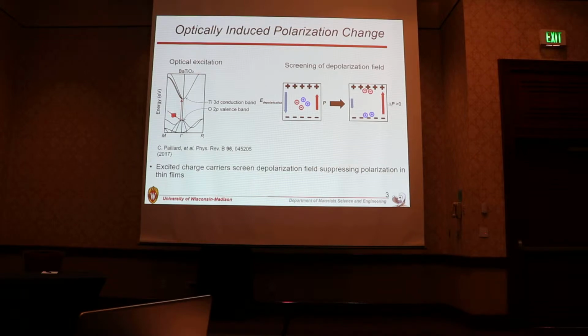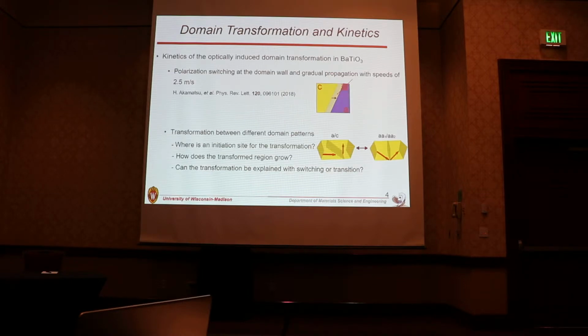It's called depolarization field screening. For a thin film system, the depolarization field is quite strong, so excited charge carriers can be driven by the depolarization field, and eventually screen the depolarization field and change the polarization. It has been experimentally proved that the depolarization field screening is strong enough to change the domain configuration before. And so, to understand the transformations, a kinetic study is quite important.